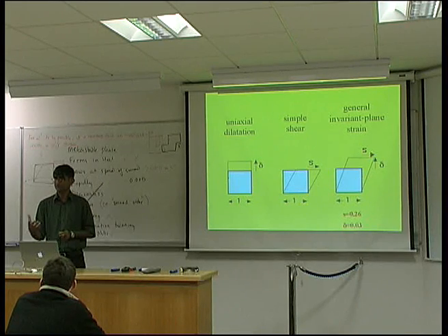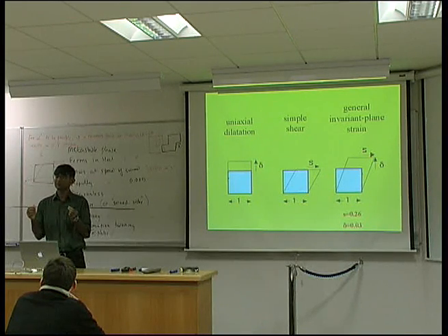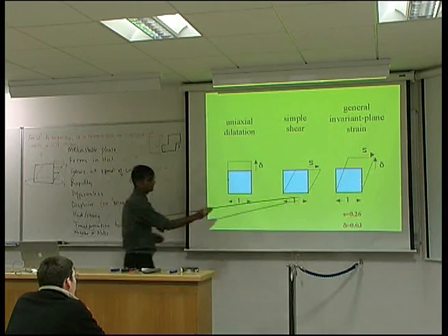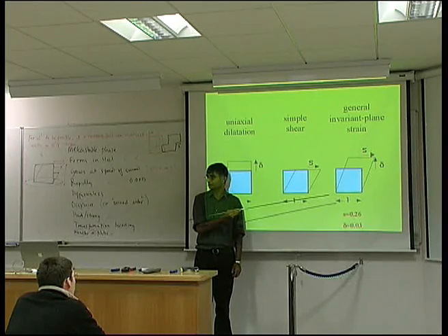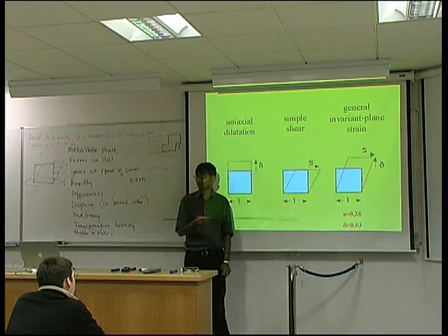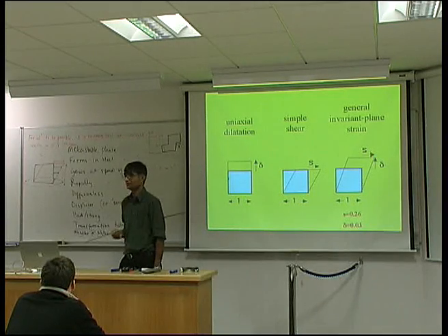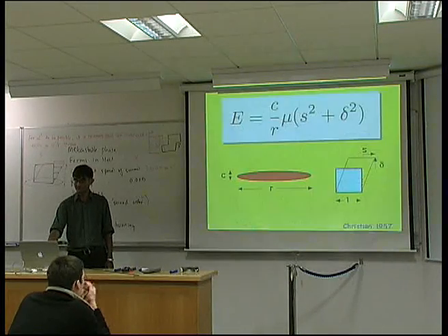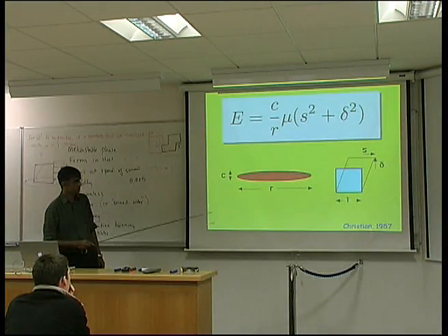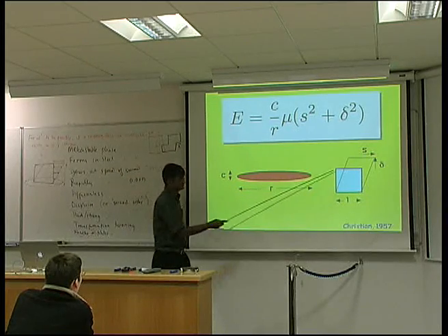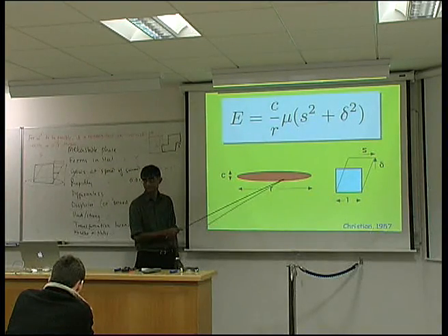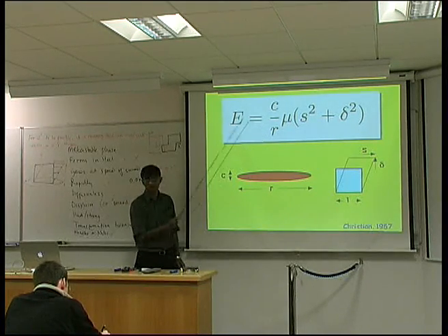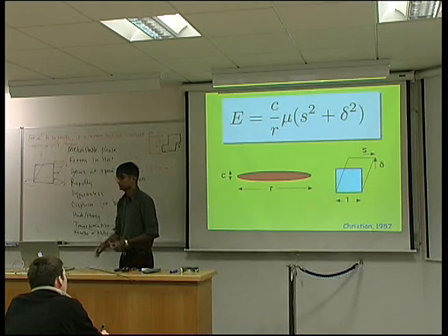Now, that could be really good news, because the minimum condition is that we needed one line coherent in the interface. We've got a whole plane here, which is unrotated and undistorted. So it appears like we have an infinite set of invariant lines in the interface. Okay. In other words, a coherent interface. This is just to show you that it is because of this massive deformation that we have a thin plate. The strain energy per unit volume depends on the thickness over the length of the plate.